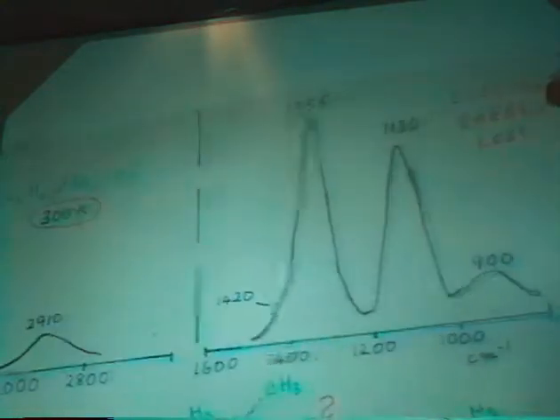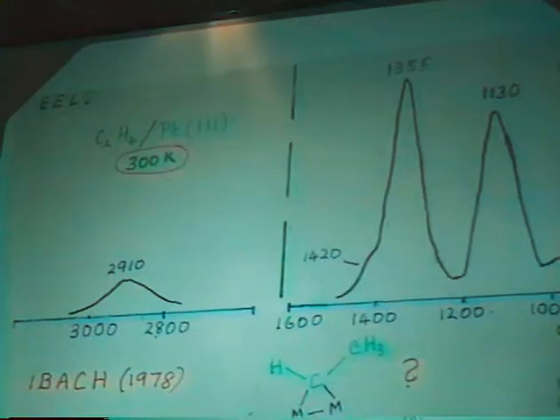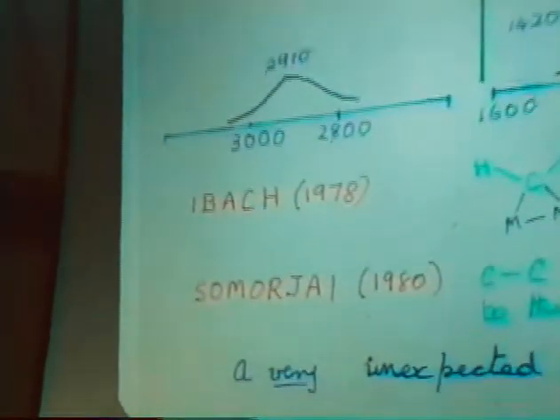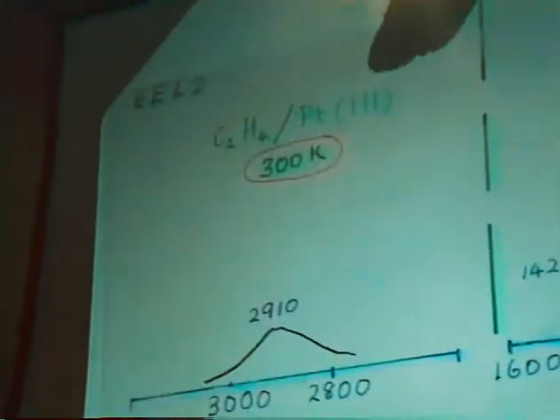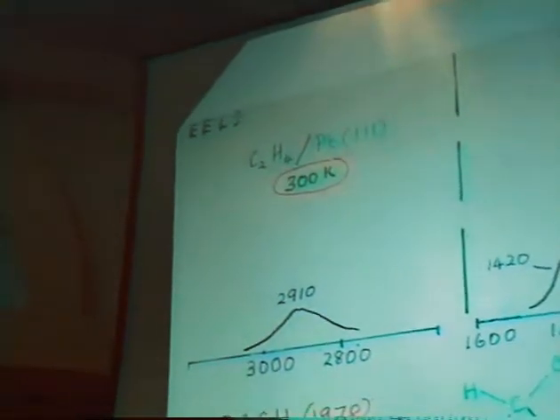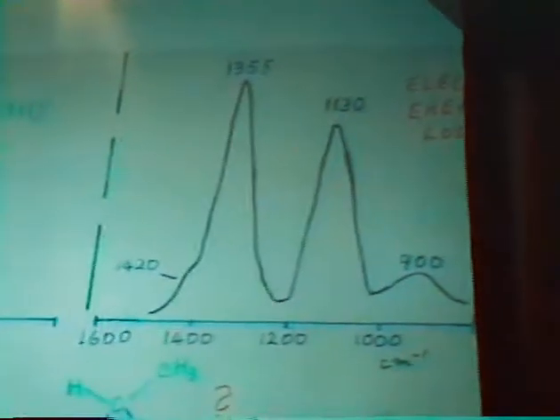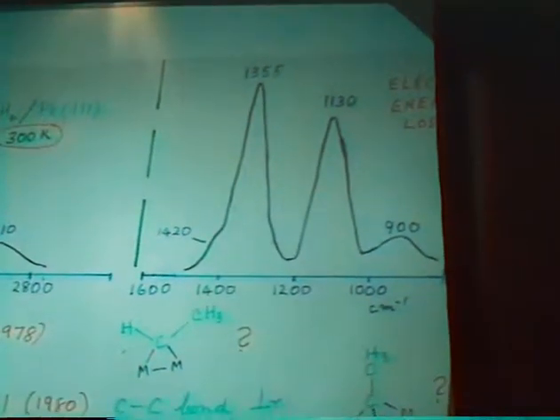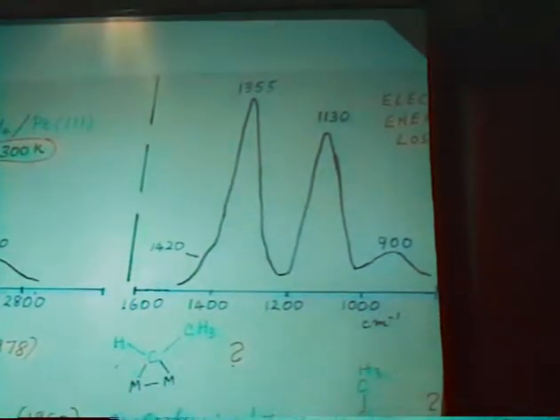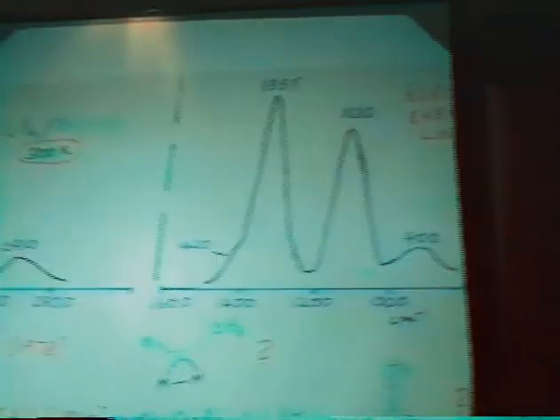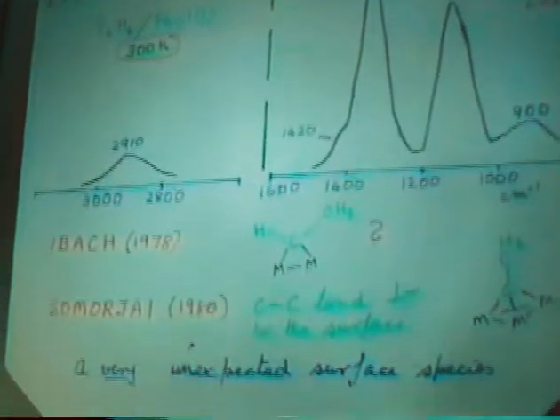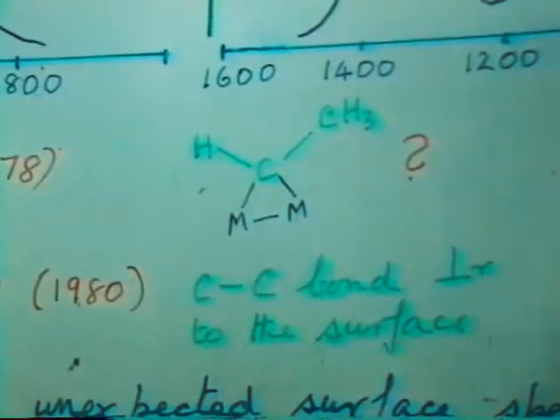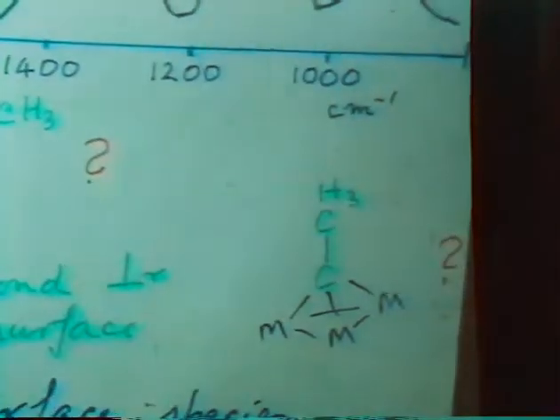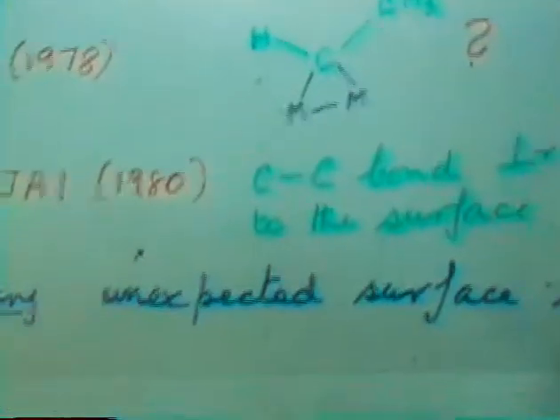And Professor Ibach applied this technique to get a spectrum of ethylene on platinum 111, which, of course, we were very interested in. Now, the resolution of EELS is very poor compared with infrared spectroscopy, typically 30 wave numbers. Today, it is just being tuned up to about 8 wave numbers at the best. But he got a spectrum, and of course, this spectrum is not offset by oxide absorptions, it goes down to lower wave numbers.